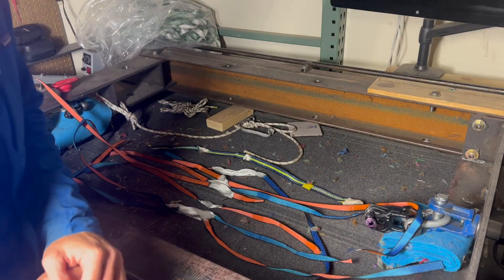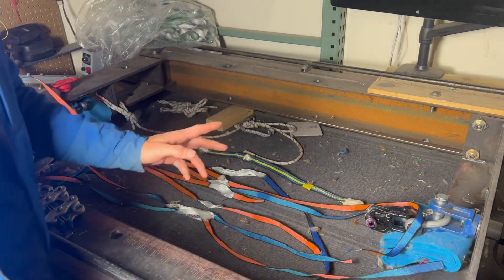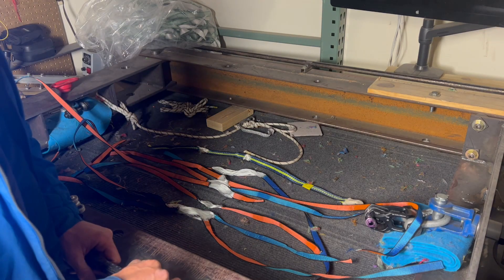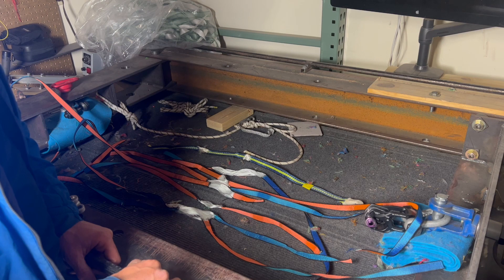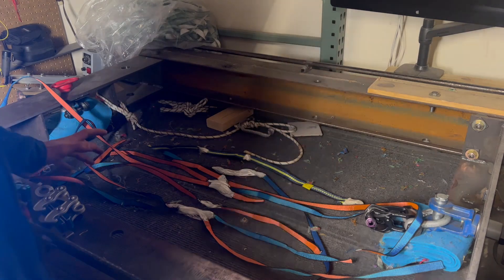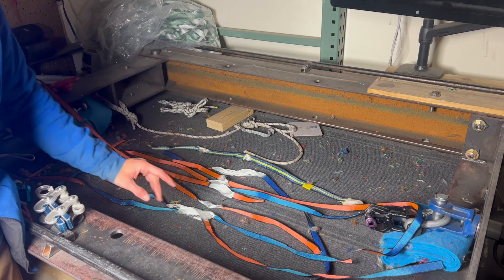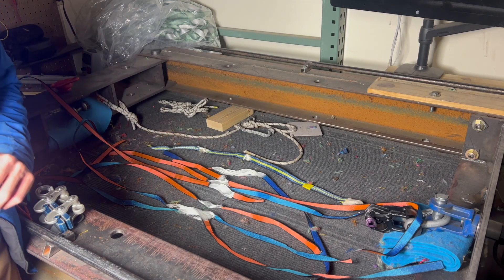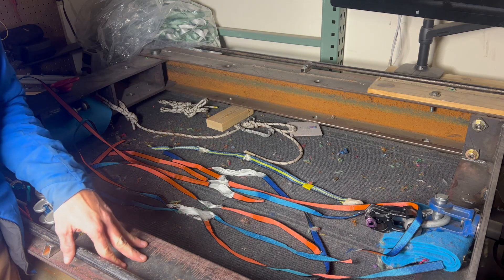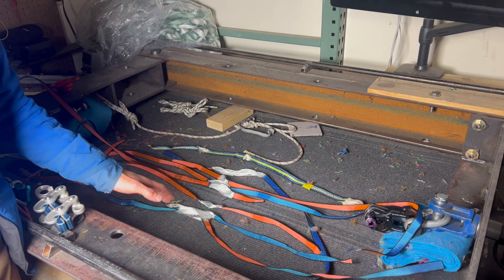We tried stacking multiple grips together — like line grips back to back — and used sliding X's between multiple grips, and nothing really improved the grip's ability to the point where I would say it's safe. So I'm here to tell you that when rigging with polyester-sheathed Dyneema webbings like these two, you should not put a grip on them, because it can and will lead to premature breaking of your webbing.